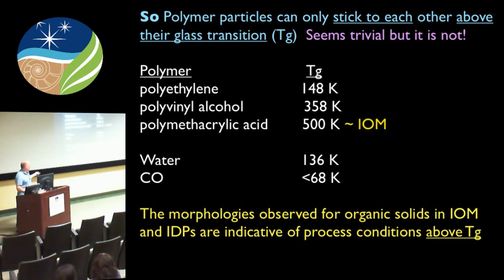And so what we're talking about chemically is that IOM is more like this than that. Now water has a theoretical glass transition of 136 K, or maybe it's actually been measured. CO has never actually been measured, but theoretically people anticipate 68 K. So what I would say is the morphologies that we've seen are indicative of processes that occurred above the glass transition. And I'm telling you, the glass transitions have to be high for this material.